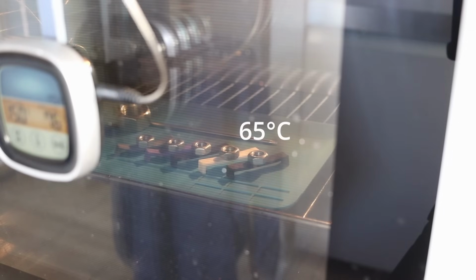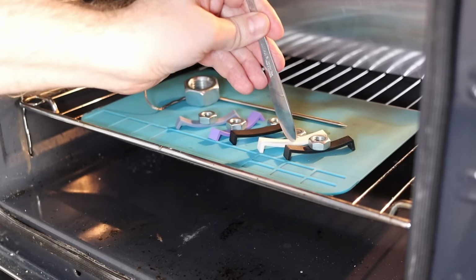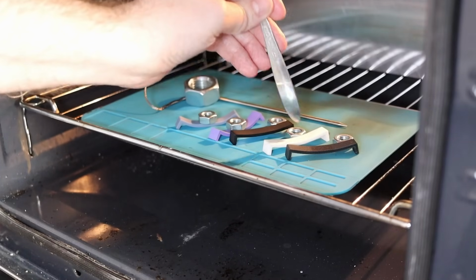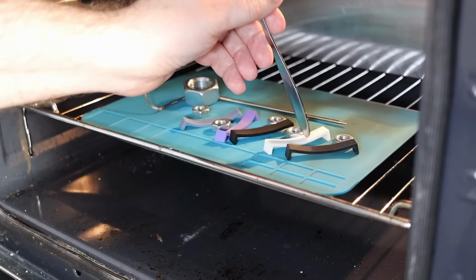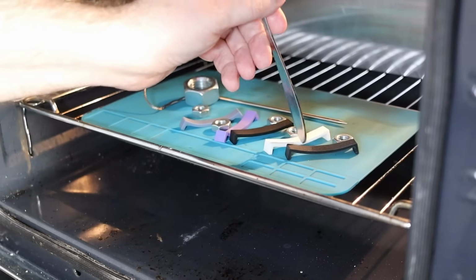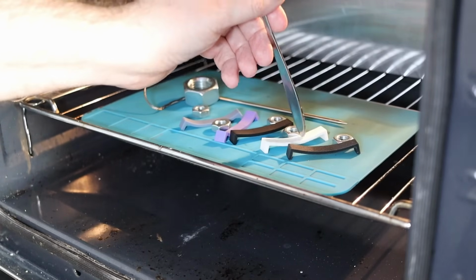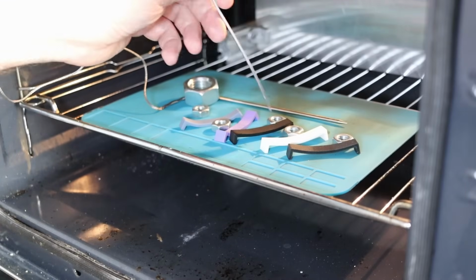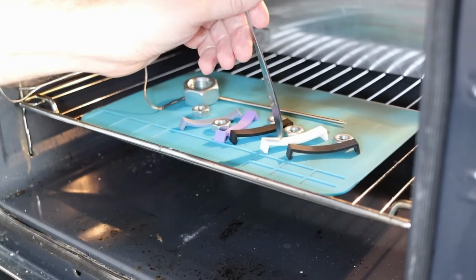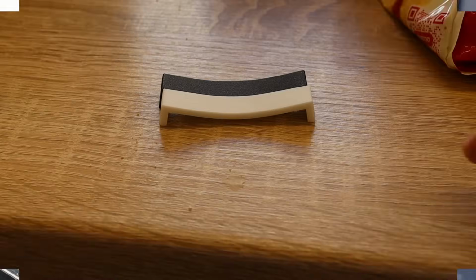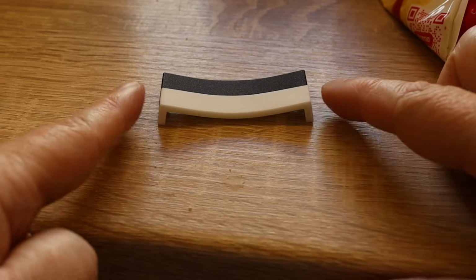This is a time-lapse speed-up video. It was hard to spot the exact moment, but the first significant deformation I could notice at approximately 65 degrees Celsius. I'll stop the experiment now because I'm curious how soft they are. Interesting to see that because of those fibers they don't deform too much, but they are quite soft, and actually this is softer than this one. These are some regular PLA filaments, and actually they are harder now than these materials here. The deformation on these two objects is very similar.